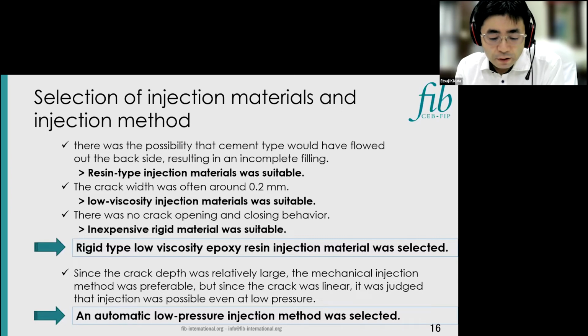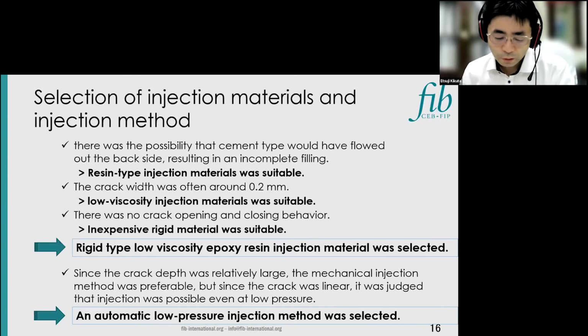The crack width was often around 0.2 millimeters. It's relatively narrow, so low viscosity injection materials was suitable. There was no crack opening and closing behavior, so followability is not required. Therefore, inexpensive rigid types was suitable. As an injection material that satisfied these conditions, rigid type, low viscosity, epoxy resin injection material was selected.